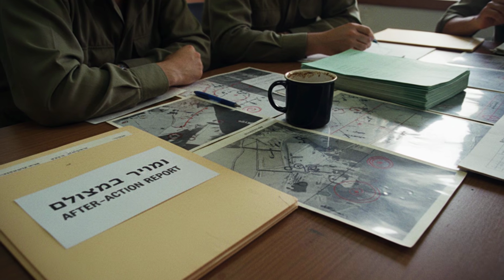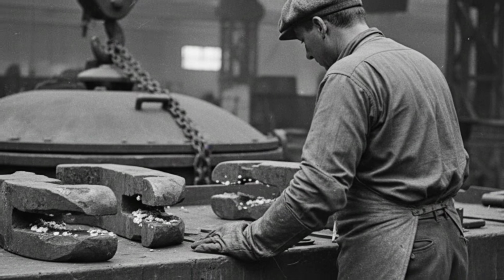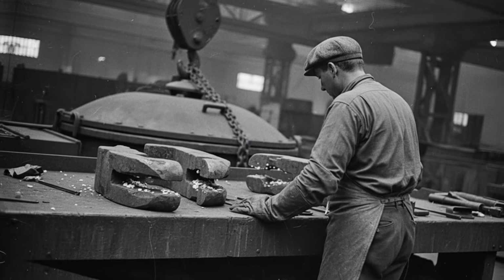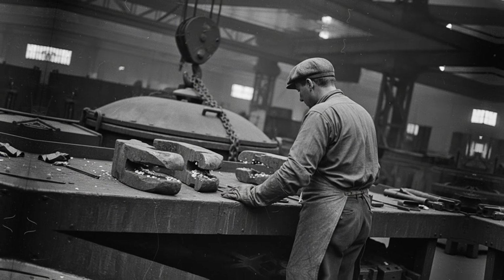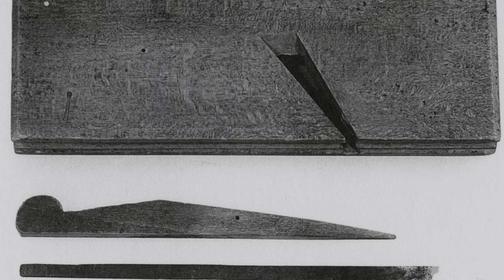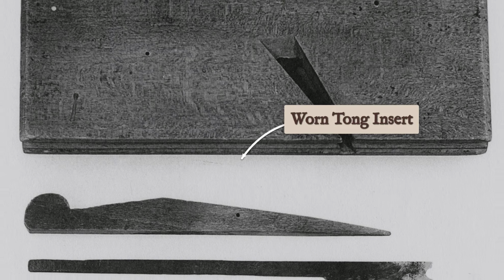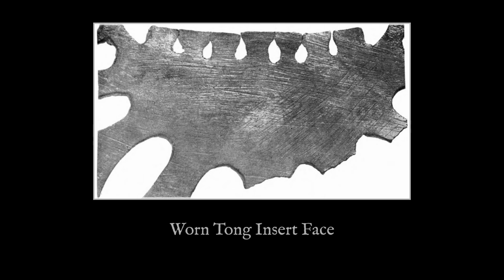The tong insert, the hardened contact face that actually gripped the ingot, was the component that determined whether a draw cycle succeeded or ended with a dropped ingot. Tong inserts wore under the combined mechanical and thermal loading of continuous pit operations. An insert that had made several hundred draw cycles had a contact geometry that was no longer identical to its original specification. The grip it provided was not the same grip the design assumed.